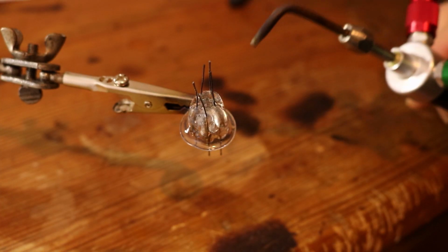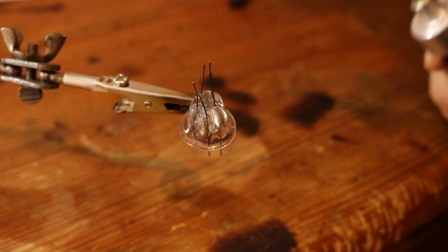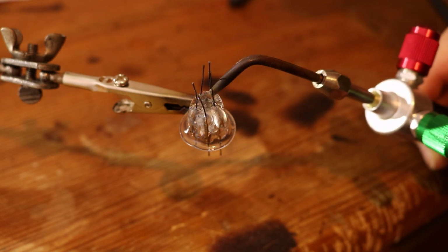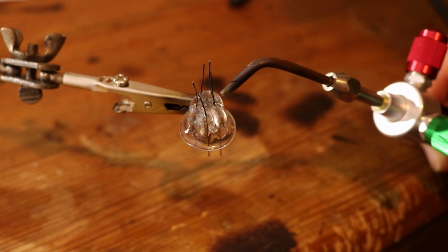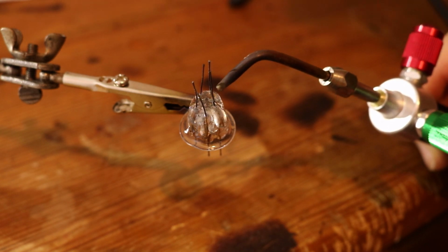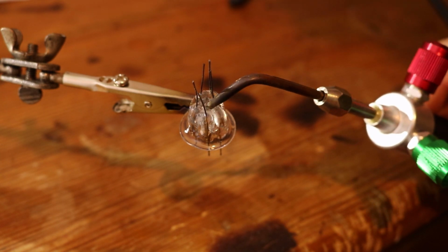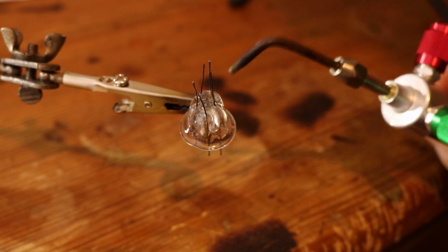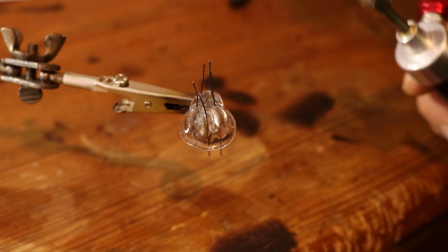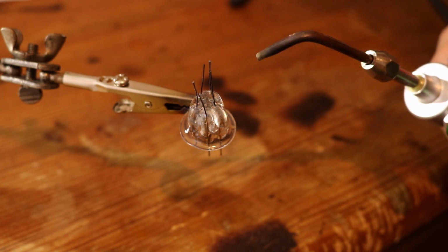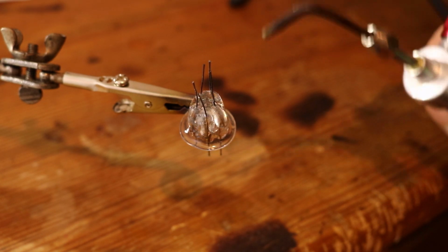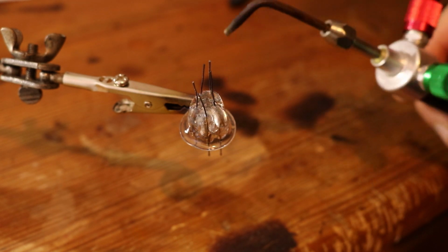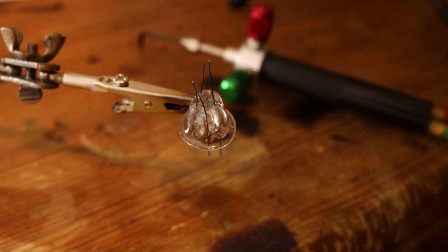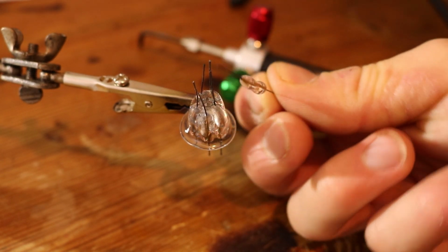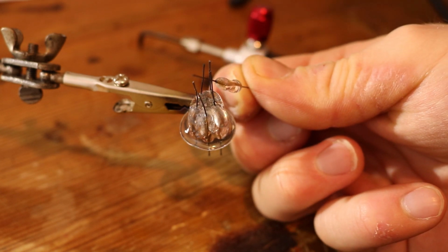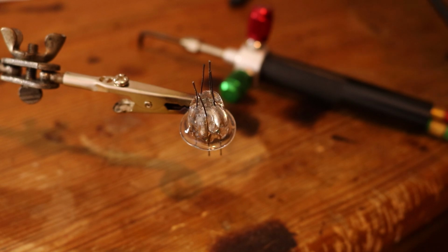This is the stem that I made, and one problem with this method is that you kind of have to get into this space here with the torch, and you necessarily attack the tungsten a bit, and then you have some residue on here on the glass, and this might be conductive. I'm going to clean this up with some hydrochloric acid, but yeah, I have to figure out a better way so the tungsten is not exposed. I tried to make the bead seals a bit higher, so it's like here, and the glass is sticking out a little bit where it's melted, but this didn't really work.